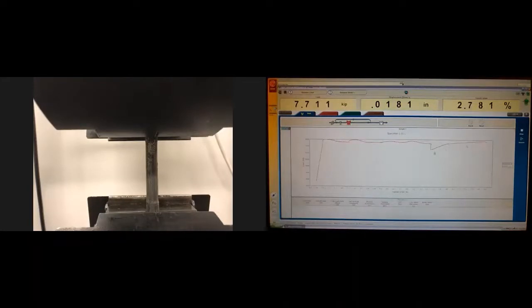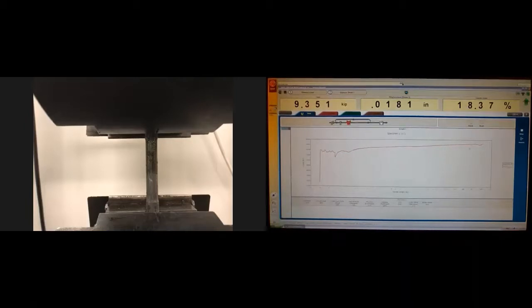So sample testing resumed, and as you can see, we're observing some increasing force, and since we passed this yield plateau with upper and lower values, you see that the material is deformed further. More and more dislocations are being generated and moved around. So from this point and up here, we see some plastic deformation and work hardening. So this is straining of the material that causes an increase of strength. Actually, at any moment we unload here, we will see the increase of this yield strength to a new level, a new limit. And this is associated with